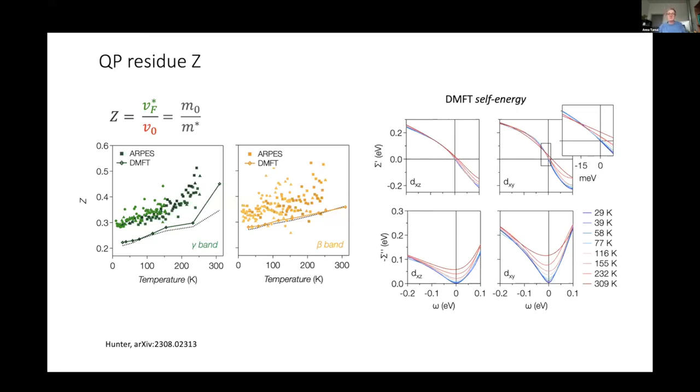If you take a good metal, if you take copper, the resistivity doesn't saturate because it melts before you reach that regime. But there was early work on some materials that show resistivity that saturates. They will have a very low, still quite long mean free path, which means that there are well-defined quasi-particles up to high temperature.